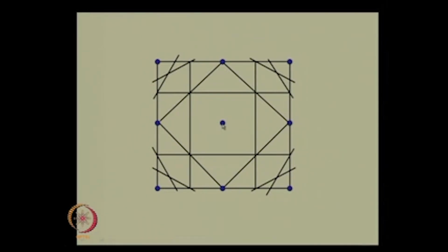around the central lattice point, we can now identify Brillouin zones based on the definition we have given for Brillouin zones, which is basically that the first Brillouin zone is the region in space around this point which can be reached from this point without crossing a single Bragg plane, and therefore that would be the region that is identified here. Okay, so, this region around this point is therefore the first Brillouin zone.